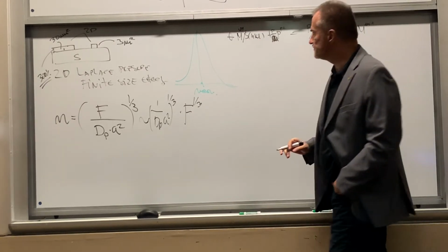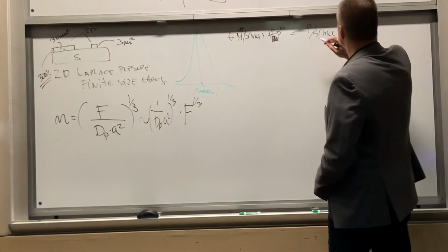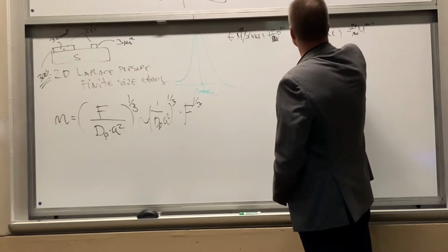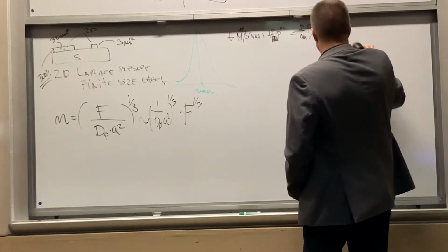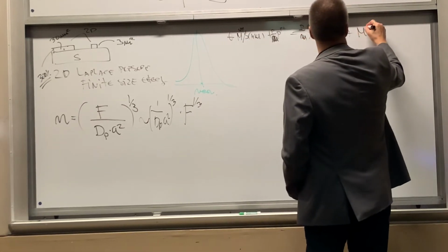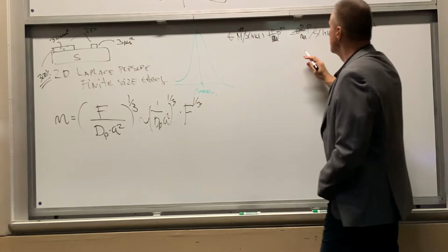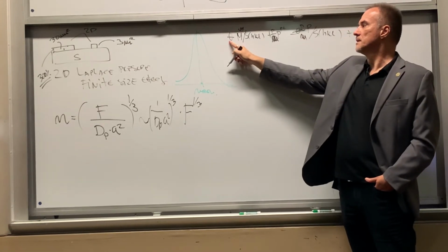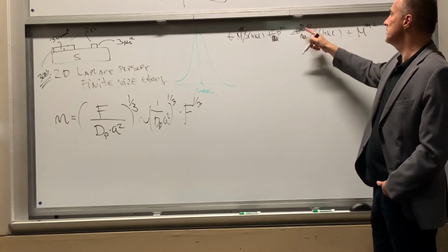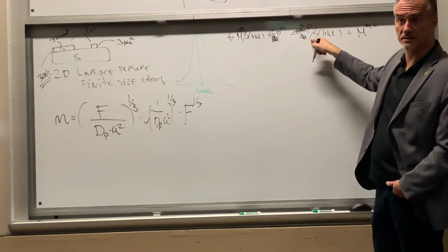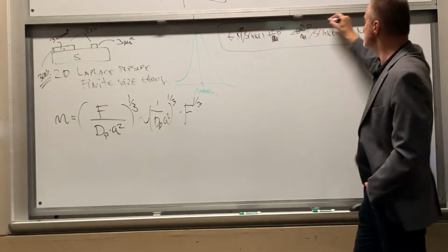Now that's the first thing. The second thing, obviously, because this theta is here and this is here, this is supposed to be like this, P over M here. But because I have this theta here, then the theta will be here too, okay? So as much coverage as I start out with of my UPD metal monolayer, that much coverage times this ratio here, I will get of my catalyst on the surface, right? So that's the full stoichiometric relation of this business we're talking about here.